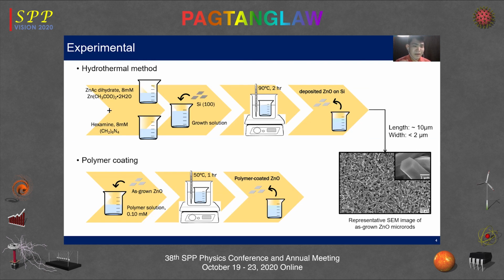Then, the ZnO microrods were coated with polymer solution using the dip coating technique. So, again, we used three different polymers, PVP, PAH, and PDDA with 0.1 millimolar concentration. Then the as-grown ZnO on silicon substrates were submerged in a polymer solution and heated at 50 degrees Celsius for 1 hour. Afterwards, the samples were harvested and air dried.